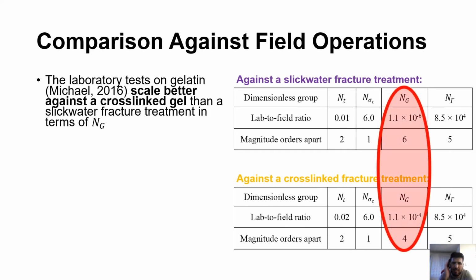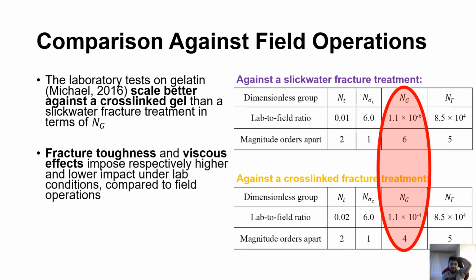When we see the elastic deformation dimensionless group, it goes from being 6 orders of magnitude apart for the slickwater fracture treatment to only 4 orders of magnitude apart for the crosslink gel fracture treatment. The other dimensionless groups are 2 orders of magnitude apart for the treatment time, 1 order of magnitude apart for the confining stress, and 5 orders of magnitude apart for the crack formation energy. Those results are by no means ideal.